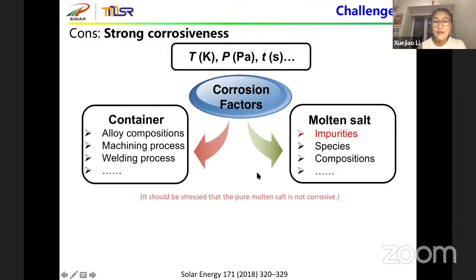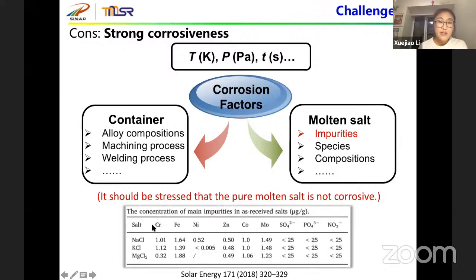For the molten salt, it should be stressed that the pure molten salt is not corrosive. That means the impurities in molten salt are the main factors in the corrosion. Besides, the species and the compositions of molten salts are also important factors. From this table, we can see the raw chlorides contain a variety of impurities. In addition to the metal elements, there are also acid radical ions. So how do we test the corrosion behavior of molten salt on a contacted alloy container?